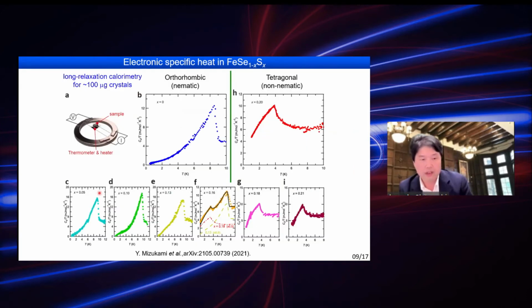Let's look at the specific heat first. Here is C over T as a function of temperature, measured by the so-called long relaxation calorimetry technique. We use pretty small crystals, but we can measure the specific heat with high resolution using this technique.